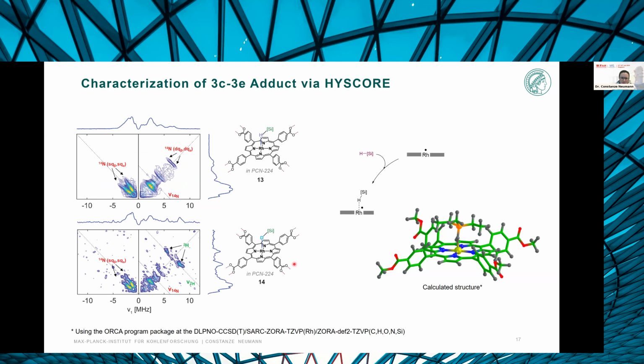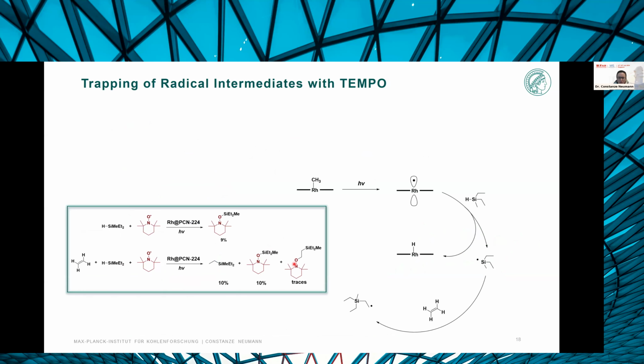catalytic transformation. And the intermediate could be further validated by Raman studies in addition with isotope labeling to confirm that it is really an interaction between the rhodium via the hydrogen versus the deuterium center. And after the sigma adduct is formed, it can then, under photochemical conditions, be split to form silyl radicals, which are engaged in reactivity with ethylene. And both of these radical intermediates could be trapped in the presence of TEMPO.